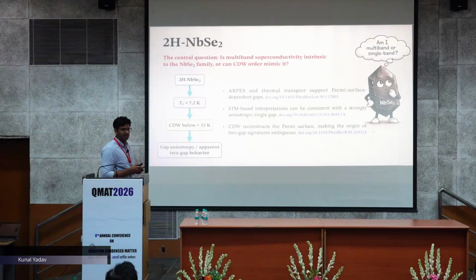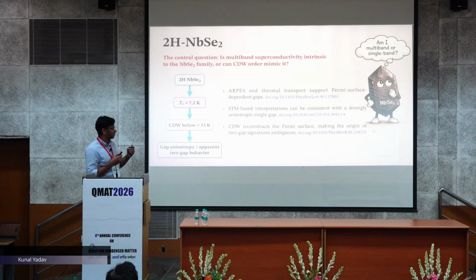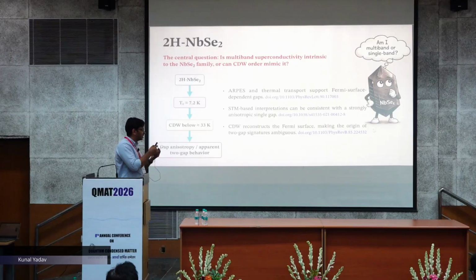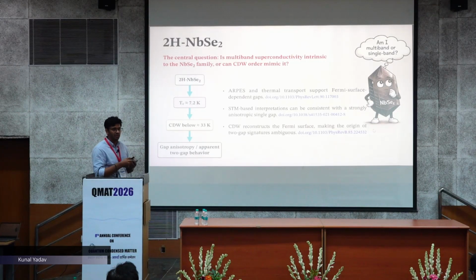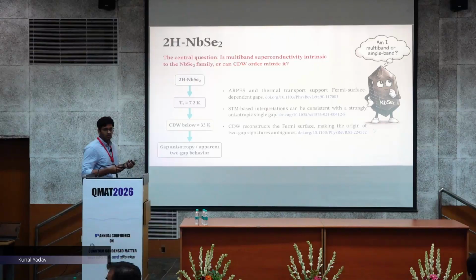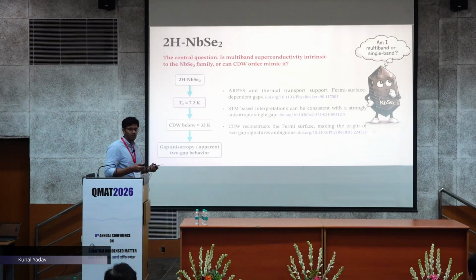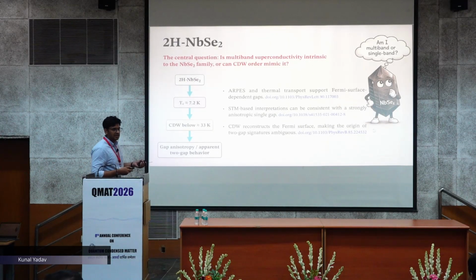So the main culprit is CDW, because some of the papers that claim it is an isotropic S-wave superconductor show that the CDW mimics it. CDW reconstructs the Fermi surface, and it mimics a multiband superconductor. So NbSe2 is itself confused. Am I multiband or single band?